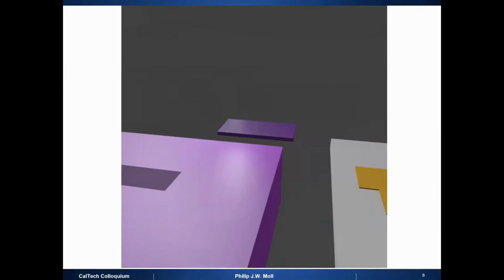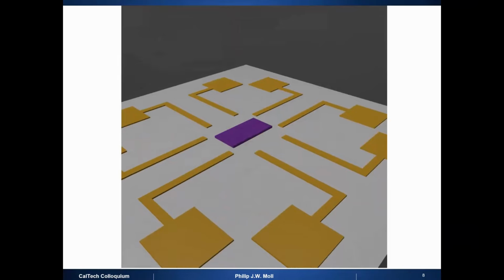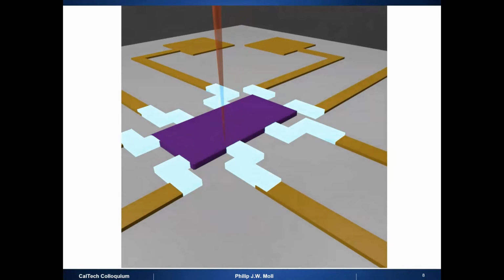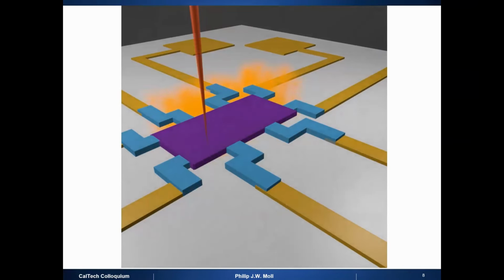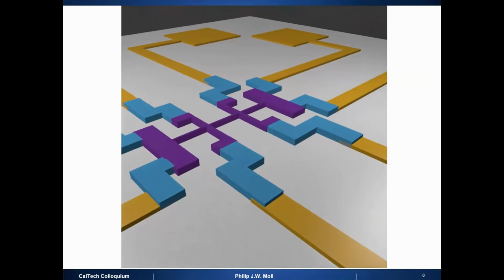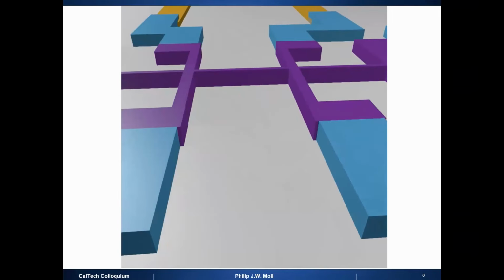Usually this is 100 micron wide, 10 micron long, and maybe a micron thick. It's then integrated onto a silicon chip. We make contacts, and then we fabricate it into whatever shape you need. This is maybe the most boring shape, because I'm not very good at Blender, but this could also be a ring geometry. This can be three-dimensional geometries.